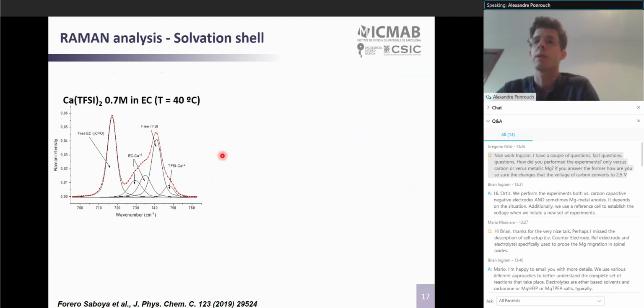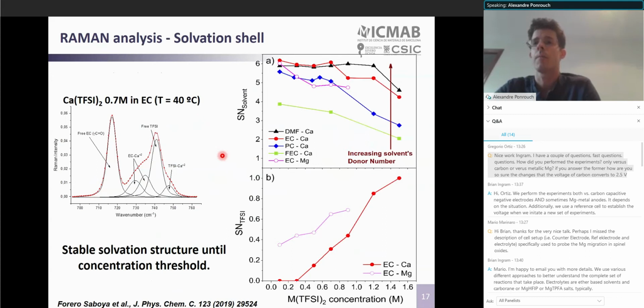So to try to quantify a bit more these issues, we deconvoluted the spectra, and we analyzed the results in terms of the amount of solvent molecules and of anions present in the primary solvation shell with respect to the salt concentration. So we have done that for different solvents: dimethylformamide, ethylene carbonate, propylene carbonate, and fluoroethylene carbonate for calcium TFSI-based salt. And we made the comparison with the magnesium system for the ethylene carbonate-based solution.